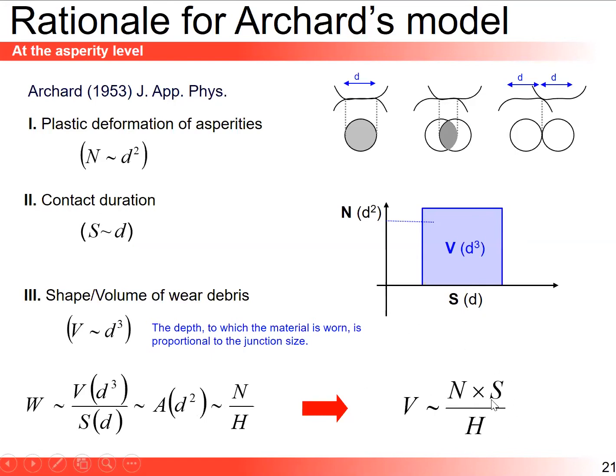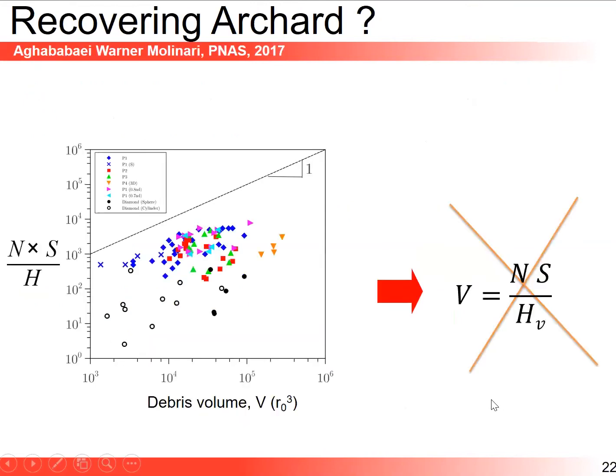Do we recover Archard's value? Okay, so we try that. We try that because we can control in our simulations the applied load N, we can control the hardness, and we can measure the debris volume V as an output of our simulations. From a debris, we take it out and count the number of atoms in there. And all those colored points represent different simulations in 2D, in 3D, different potentials. And you see that we don't find a correlation between those two quantities. Okay, so we don't recover Archard.